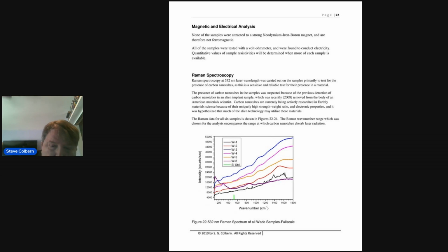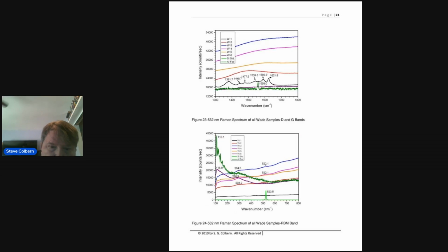Next slide. There were some peaks in sample W1, which I believe later turned out to be peaks from aluminum oxide, but in the high frequency or high wave number region. But in the low wave number region, there were a couple of peaks that could have been single wall carbon nanotubes, and